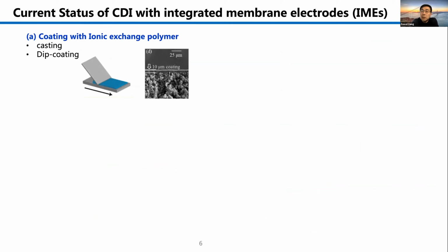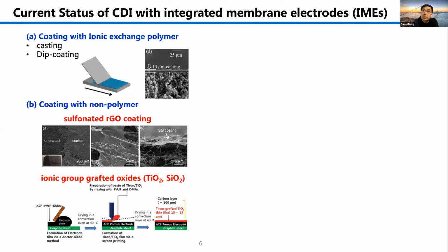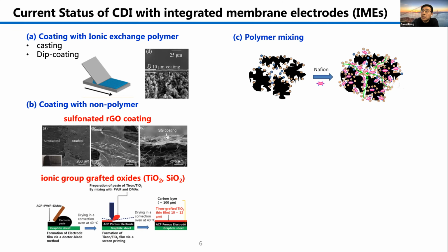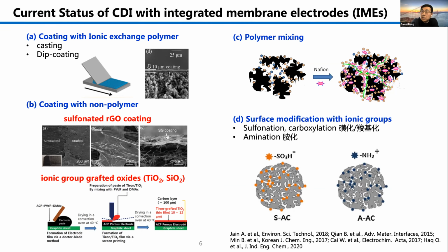To reduce the usage of the membrane, you could make an integrated membrane electrode by using coating, casting or dip coating, coating with ion exchange polymer, or sometimes even non-polymers could solve the problem, like sulfonated RGO or ionic group grafted oxides. We could also use polymer mixing to realize it, but it reduces the charging rate or ionic transportation rate. And the last one is quite similar to the previous one, just making a surface modification with the ionic group.